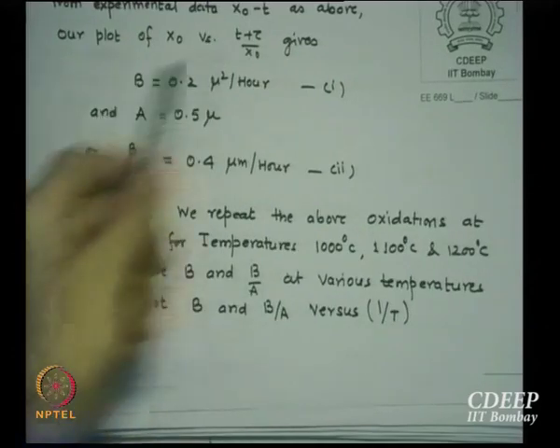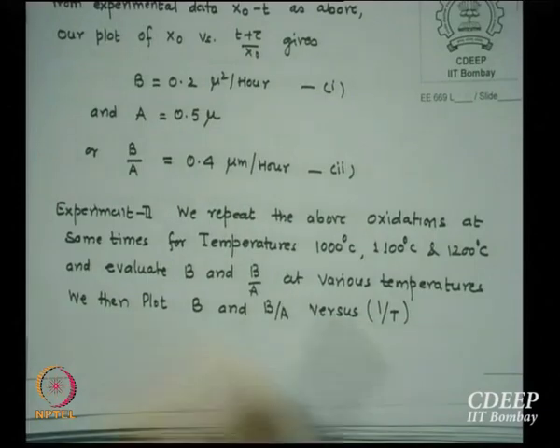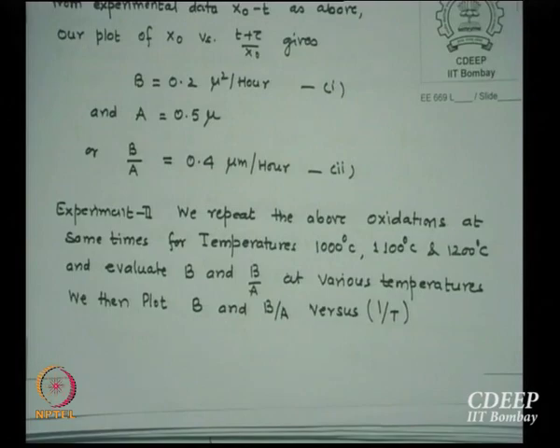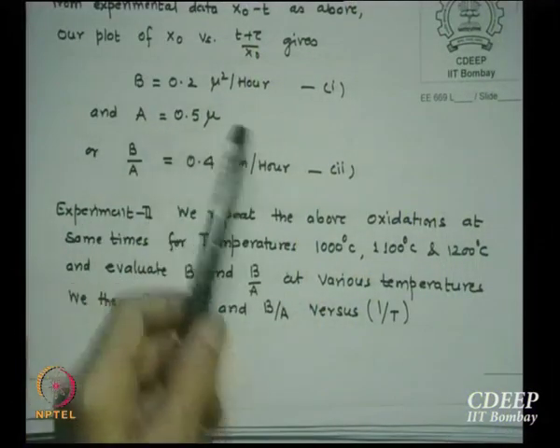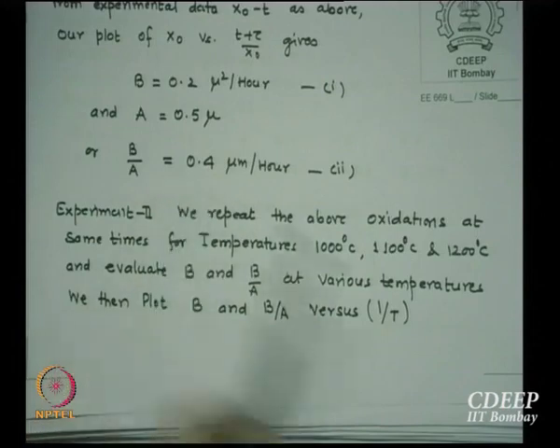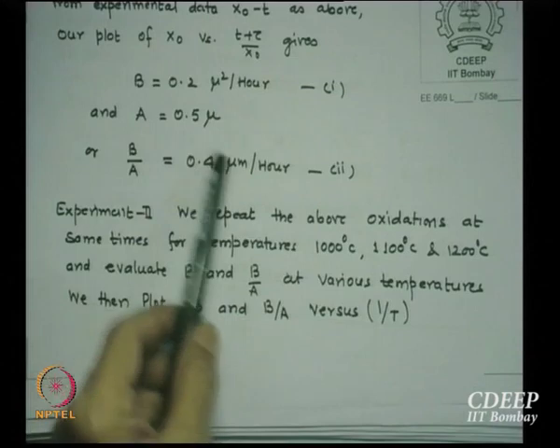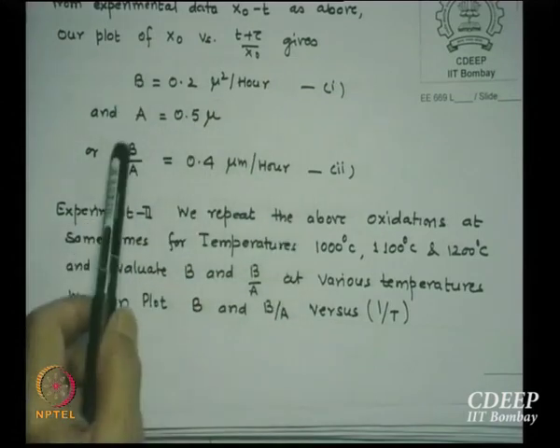So let us say a typical experiment which I did, or rather someone else had done, of course I have calculated, but this data was taken from our lab many years ago. So B is 0.2 micron square per hour, A is 0.5 micron, and B by A therefore is 0.4 micron per hour. So I just now said if I know the data, I will be able to plot time versus x0, and if I know this, I will be able to evaluate B as well as B by A.